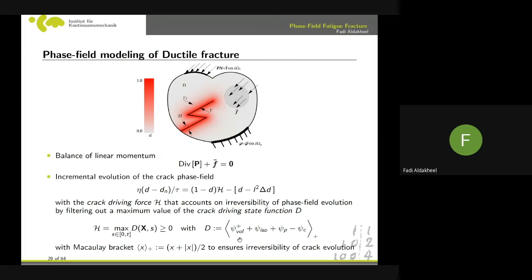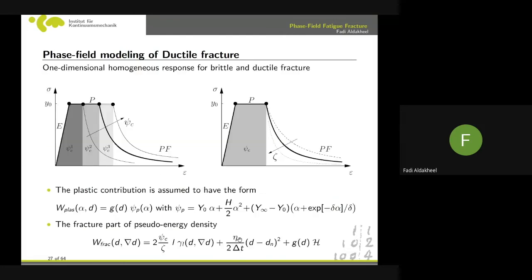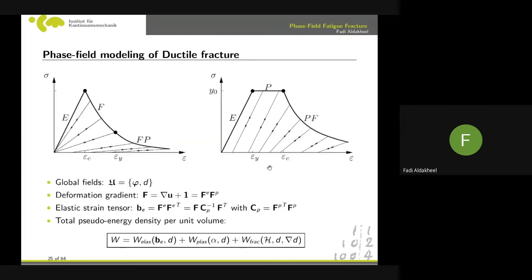However, in the literature, there are other ways. You can also use stress theory. It's not restricted to this one. You can use the stress, for example, let me go back here, maybe here is easier. When the sigma or the strain reaches some critical value, the fracture can start. Or you can use a stress criterion, or some other criterion, for example, here I have von Mises plasticity. If you think about another plasticity, one can also make it more general, in terms of what kind of criterion one needs to use.